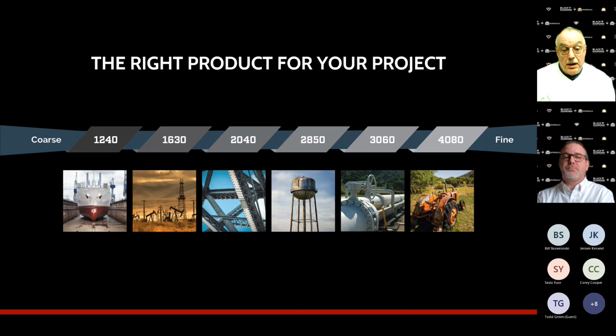The reason that's important in a blasting operation is because we've done several tests in the same material. In fact, even in the U.S. Minerals iron silicate, the copper slag, and on new steel, we compared let's say the 2040, which is a larger material, to the 3060, and we did the same exact test. Well, it turns out that the 3060 on new steel will cut faster with less material per square foot than the same material in the 2040.